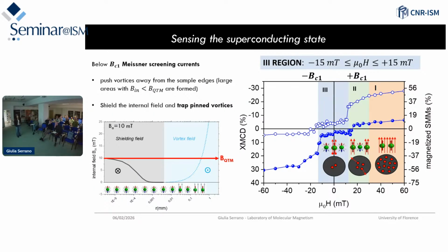That is actually the Bc1, the first critical field of the superconductor, at which the Meissner state happens. So in this state, vortices are suddenly pushed out of the bulk of the crystal. So we have a lot of molecules that are doing this quantum tunneling of the magnetization. But we also have the shielding, the screening Meissner currents that preserve the internal field. So the few vortices which are trapped inside the superconductor cannot exit anymore.